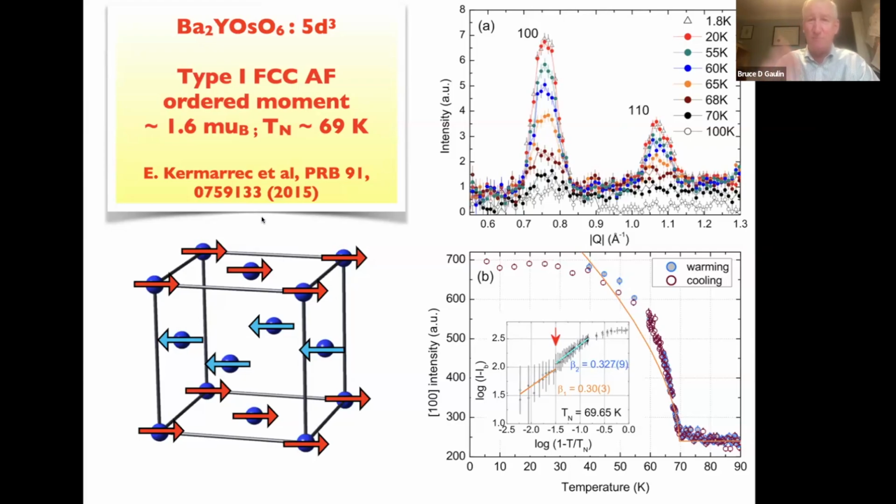And one can look at the magnetic Bragg intensities and try to fit to an ordered structure. Actually, the ordered structure that we fit to was more or less the simplest one that we could come up with. And the purpose of doing this was really to estimate the ordered moment associated with this structure. It wasn't necessarily to solve the magnetic structure because we didn't have that much information, right? There's only a few Bragg peaks that are observable. But nonetheless, we modeled our data, based on this single K antiferromagnetic structure, which means that the moments are arranged in planes